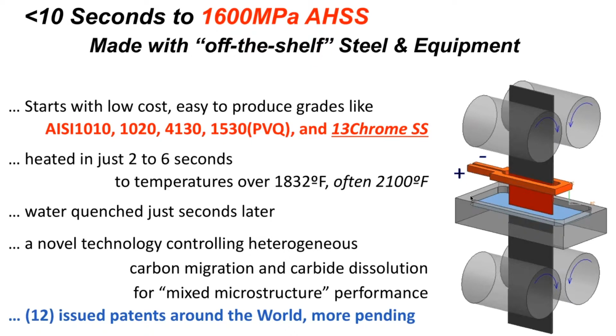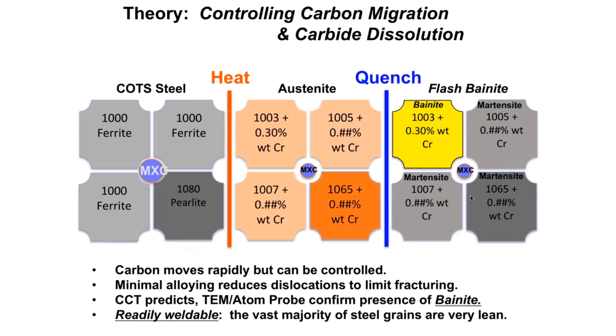Most people, when they do steel heat treating, they think of homogenization. If you can imagine steel in the melt ladle, of course there it's homogenized. That's how they check the chemistry to make sure that the steel is the alloy you're looking for. So if you could imagine, we're going to talk about a steel today, 4130. Well, 4130 is about 0.85 chrome, 0.15 moly, and of course, 0.3 carbon, where it gets its name. But in the melt ladle, it's very homogenized.